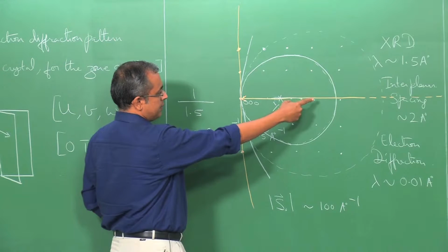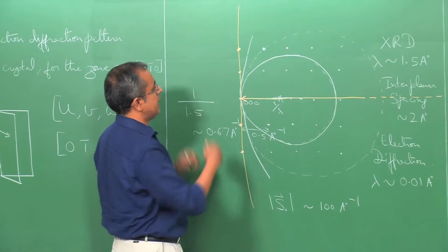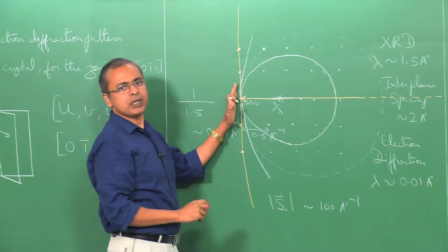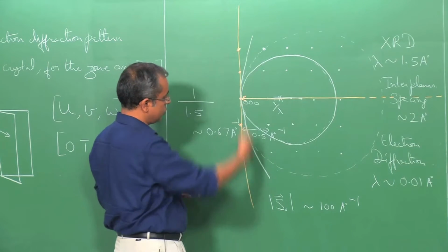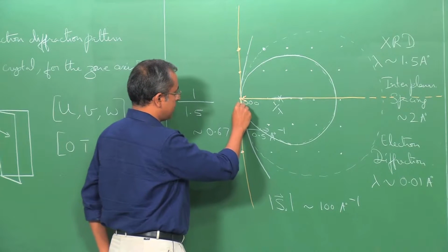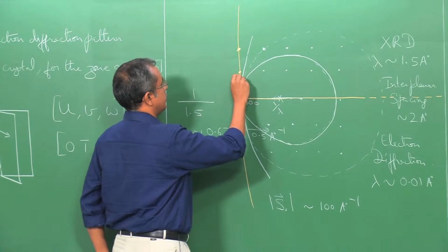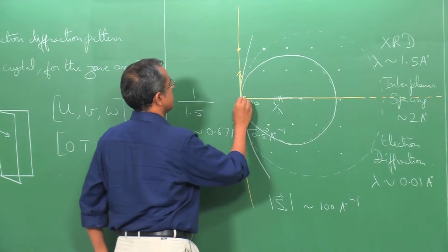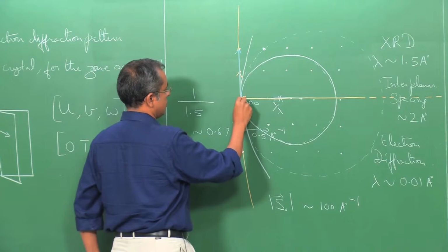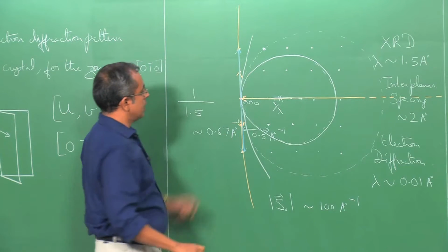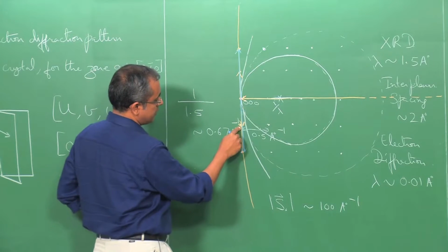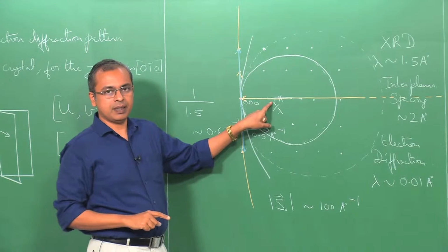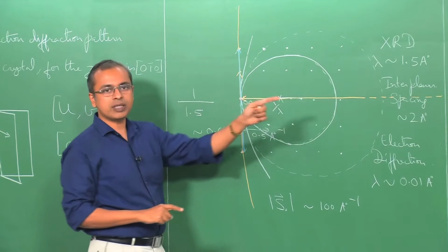Here this wave vector, as you can see from the diagram that we have drawn, is perpendicular to this direction that you have here. It is actually perpendicular to this plane, of which we are only seeing a 2-dimensional section. So, you are seeing a line. Therefore, all of these vectors that you see here, this is one vector, this would be another vector, these are all vectors that are going from the origin 0 0 0 to specific reciprocal lattice points. All of those vectors are actually perpendicular to this long vector, which is your incident beam vector.